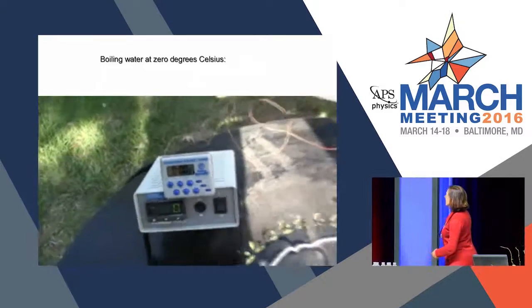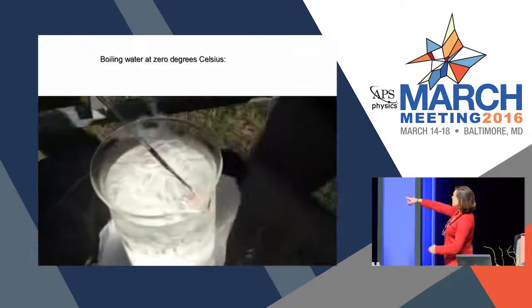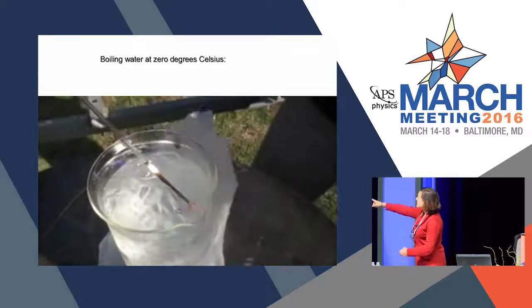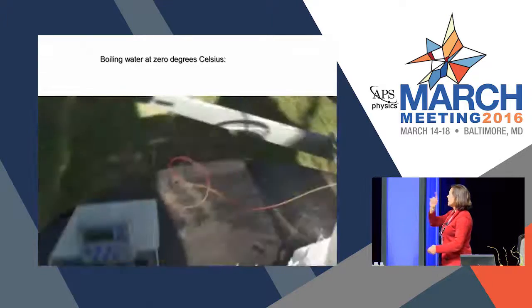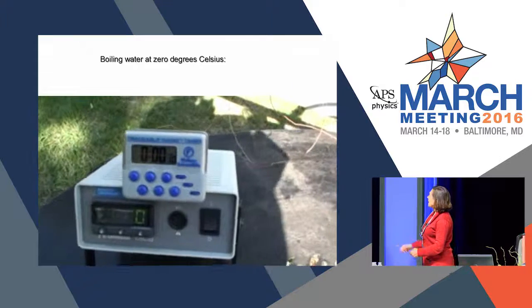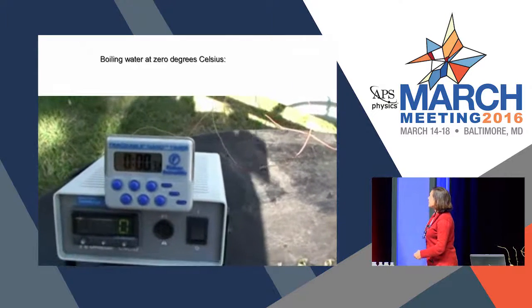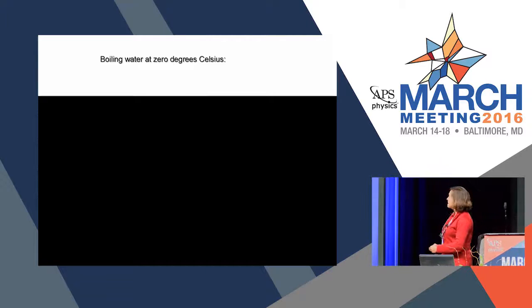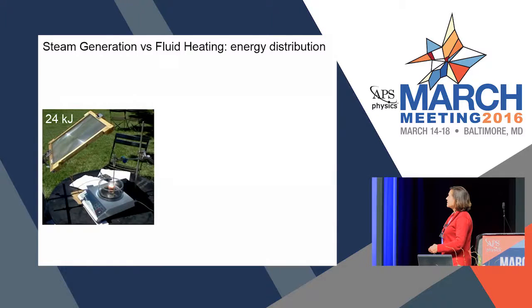Okay, so here we have our thermocouple at the bottom. That's a timer for dramatic effect. And there's our test tube in ice, and we focus sunlight. So you can see we don't use a solar simulator. We actually use sunlight, and you can see that within less than 12 seconds, we had a release of steam, and the temperature of the water remained at 0 Celsius.